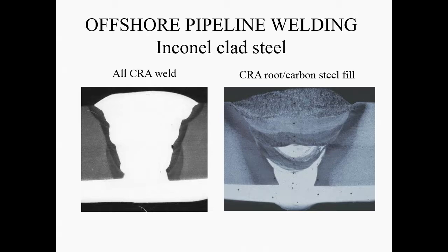But then the cap pass, that looks like the API. So you put the clad on any of the API plates. So this is an API plate. But you also notice there is something in the middle, which is neither that nor this. So the second method is to use a consumable made from the clad material, like here, just for the root bit. Finish the weld with an electrode made from carbon steel, but in the middle we put a buffer which generally is made from pure iron.